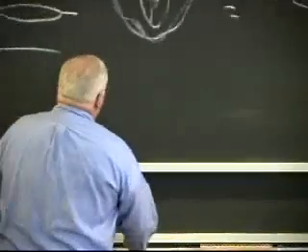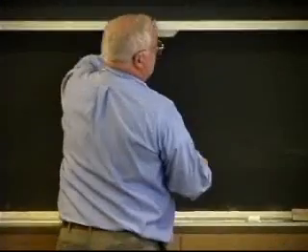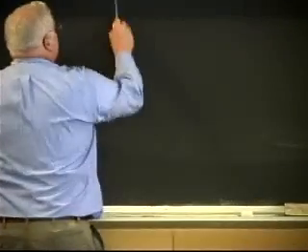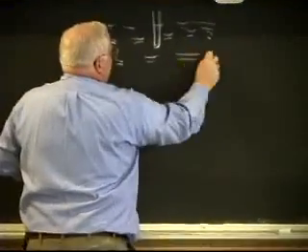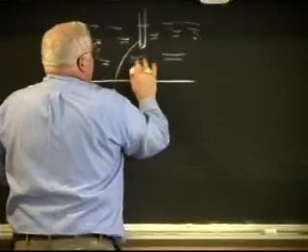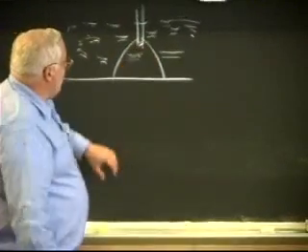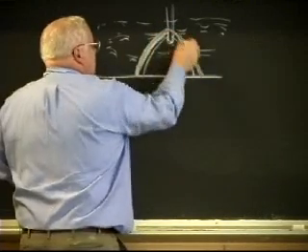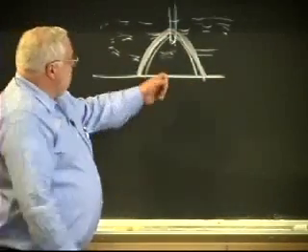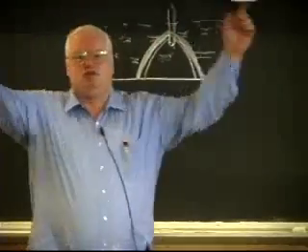And in fact, one of the problems with submerged arc welding, actually not a problem, but one of the features of submerged arc welding, is that you have your electrode, and you have this bed of sand, this flux, above the plate. You have this cavity in here that the expanding gases of the hot arc have built, and you now have a glass slag layer, a molten glass. This process could be working at 600 or 800 amps. I've got a plasma jet that now is going to throw sparks all over everywhere.